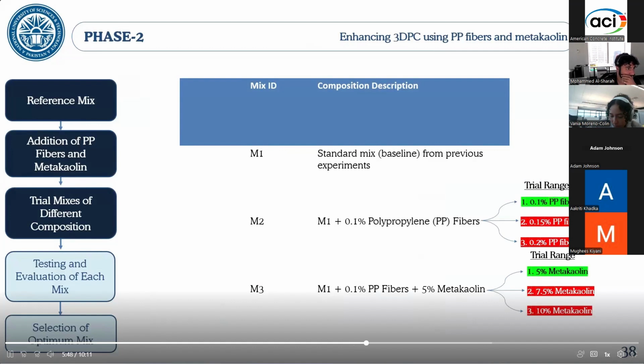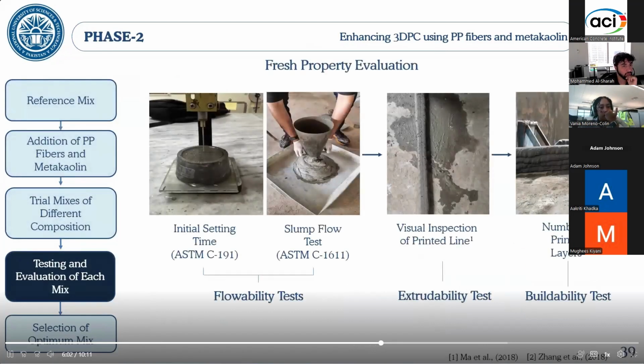Furthermore, to improve the thixotropy of our mix, we added metakaolin to it. This is the trial range for that. Above 5% dosage, the open time of our mix became far less optimal for printing, hence we went with 5%. Again, for these mixes, we performed the same tests as those used for our base mix.